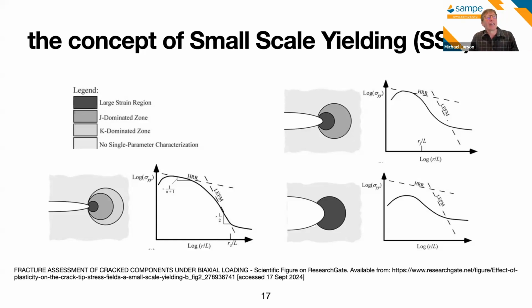known solution. And in the upper right corner here, back in the 60s, John Hutchinson and Jim Rice at Harvard developed an HRR solution that actually described the stress field a little outside of that zone, where we could extend our modeling and understanding. And usually it's the J integral, a path independent integral where we can compute the energy around a crack tip and do that in a zone even where there are some nonlinear mechanisms at play. And we, in fact, in the analysis to come, will employ the J integral for that purpose.